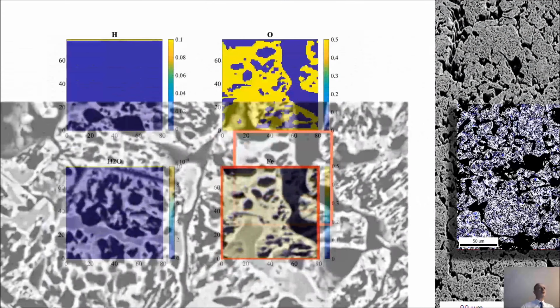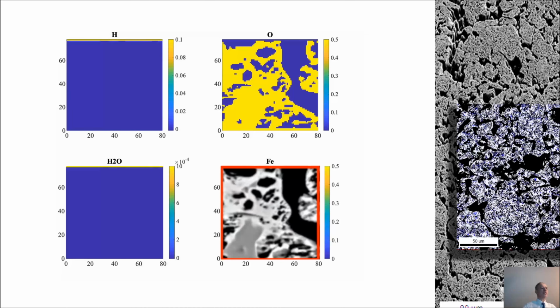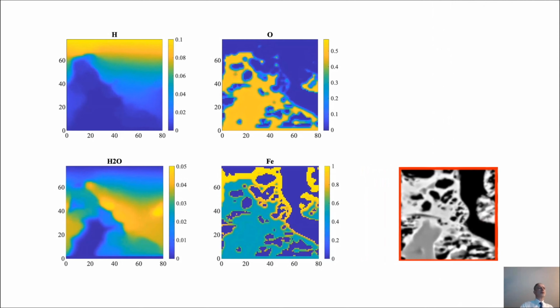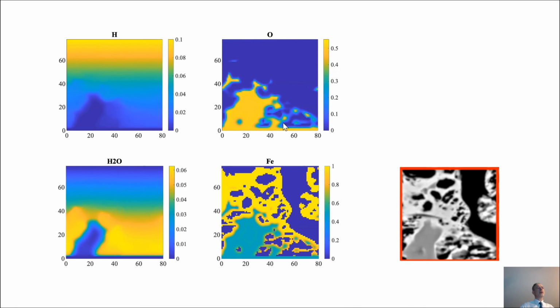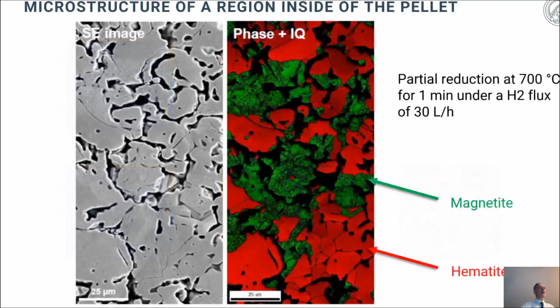When you look a little bit closer at a higher resolution after some reduction state, and we look at this later in much more detail, then you can indeed see after a certain reduction time a very complex internal structure with inherited porosity, but also with newly acquired porosity, which is due to the mass loss. Let us look a little bit closer to this. You can put this now into full field simulations, the details of which will be subject to a separate lecture. This will not be discussed in this lecture. And then you can, based on this real microstructure of the pellet, do corresponding simulations how the reduction of the wüstite is progressing under such geometrical confinement conditions. So there's in principle a Ginzburg-Landau phase field simulation behind this.